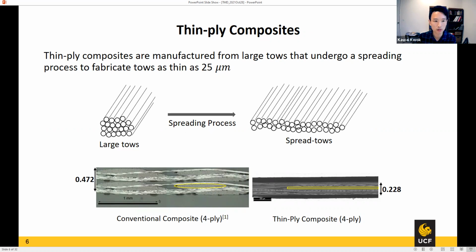But there is a technique that spreads out these tows, and the end product is a spread tow of carbon fibers. And now the aspect ratio is a lot higher. If we take a look at the difference between the resulting composites, on the left-hand side is just a traditional composite. The tow is circled by the yellow ellipse, and that is the original one.